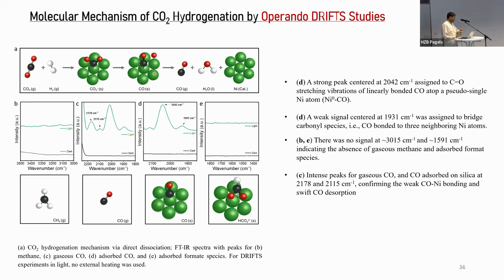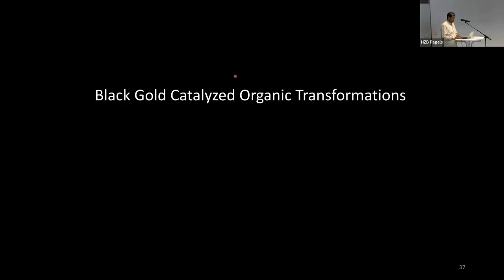And there, the hydrogen, which is again dissociated by the plasmonic black gold nickel, that dissociated hydrogen reacts with this oxygen and converts that oxygen into water, and you get a free nickel state back. And then another cycle of CO2 reduction can work. So this is a typical molecular picture of how the CO2 hydrogenation is taking place on black gold nickel. Right, so that is all about the black gold nickel converting CO2 into CO.